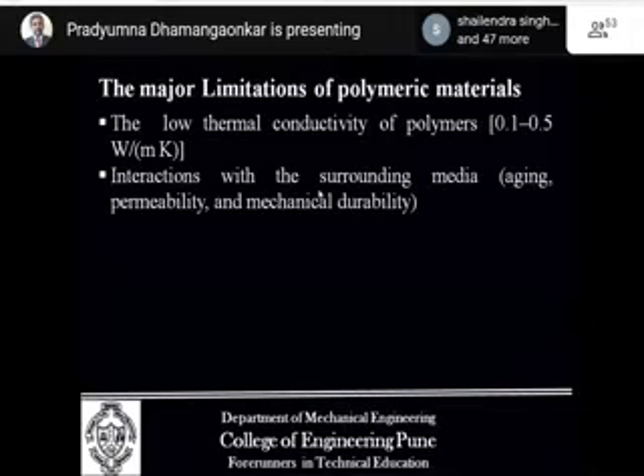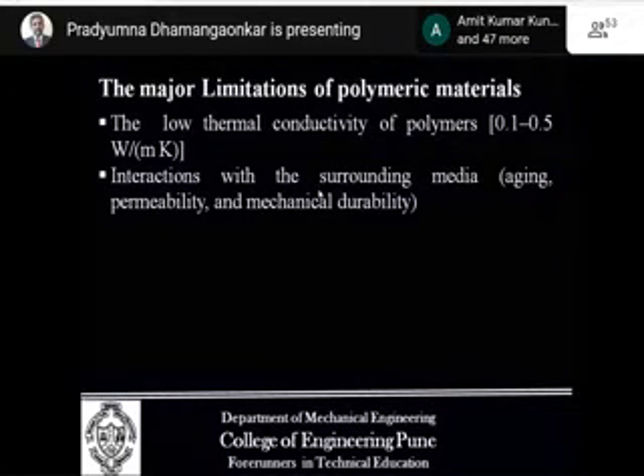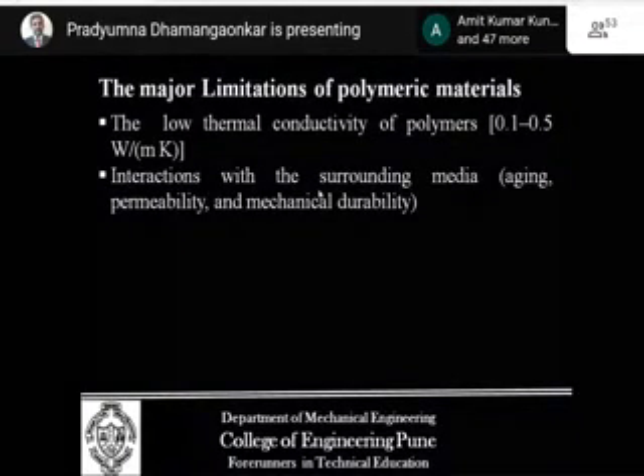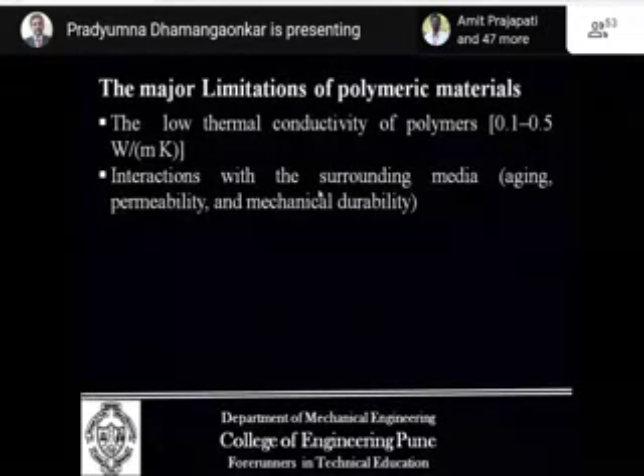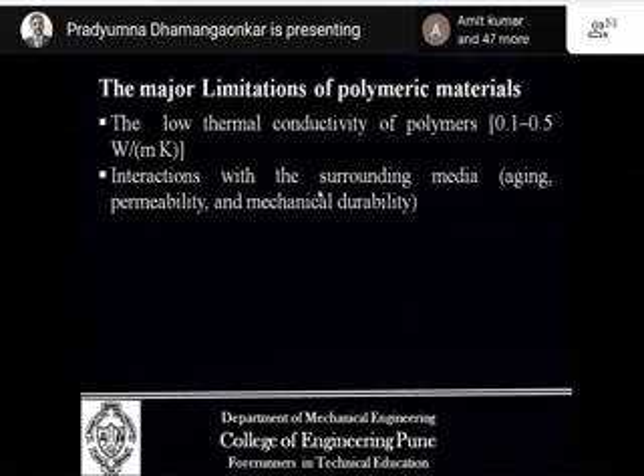Interactions with the surrounding media, that is aging. As we know that if we keep a polymer or a plastic material outside our house, after some period of time, some months, we find that that plastic or polymer gets decayed. It loses its strength, it loses its quality, and hence this is one of the major problems with the polymer heat exchangers, that it has an aging effect, and thus there is a problem with the mechanical durability.